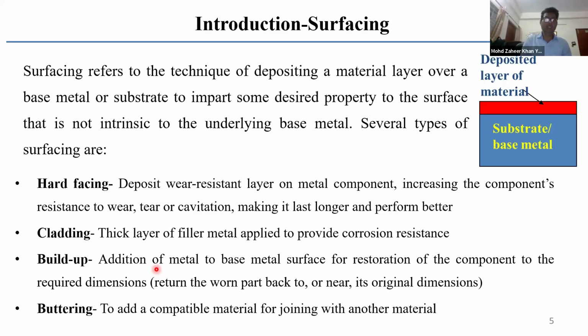To give you an example, let us say we are interested in joining mild steel with stainless steel. So if mild steel is joined with stainless steel directly, then mild steel has a higher percentage of carbon. Stainless steels generally have a very low percentage of carbon. There will be carbon migration taking place from the mild steel to the stainless steel side. The carbon that has migrated to the stainless steel side will actually react with the chromium to form chromium carbide, and the stainless steel will get sensitized or it is likely to get corroded. So in this case, before the components are joined, a third material, generally Inconel, is deposited on the stainless steel, and when Inconel is deposited, there is a sufficient amount of chromium, so the phenomenon of sensitization will be prevented even if some carbon is migrating. So this is another process of surfacing known as buttering.